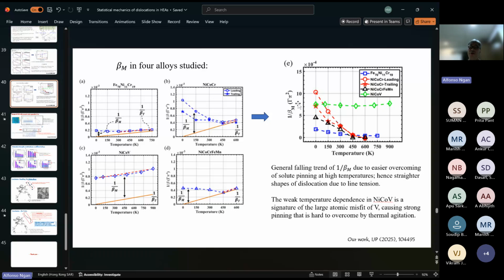This one is proportional to the resistance to dislocation. So that will be just the fluctuating fault energy effect. The other effect could be from the Peierls stress as well, but we are not addressing that in our analysis so far. Although we would expect that the higher the lattice distortion, the Peierls stress should go up.